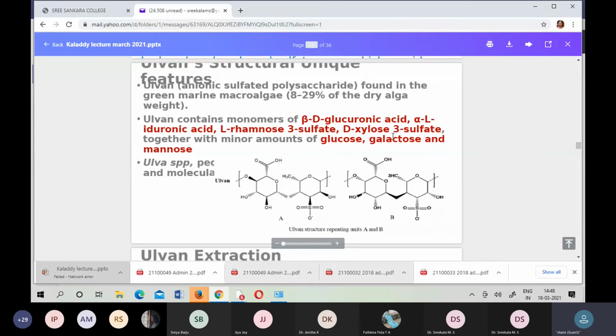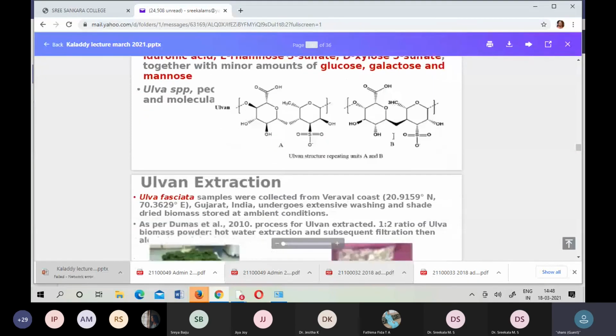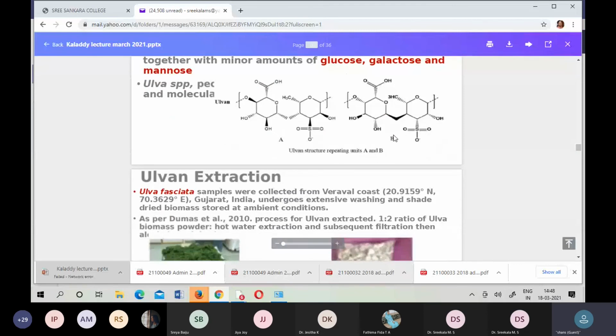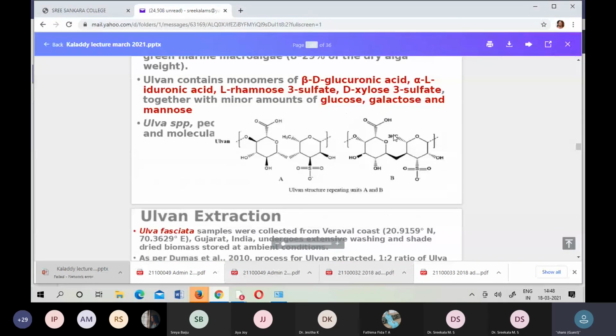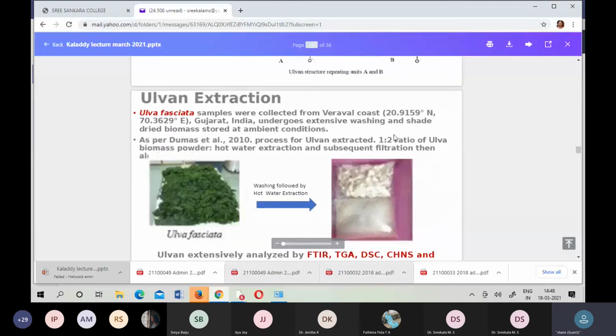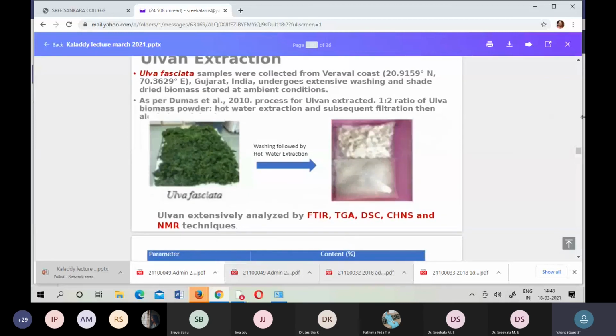So how much can we extract from this Ulva seaweed? It is close to 8 to 29% of algae dry mass. We get this sulfated seaweed polysaccharide. So how to do the extraction? We collect the samples and we wash, we dry, and we do everything.